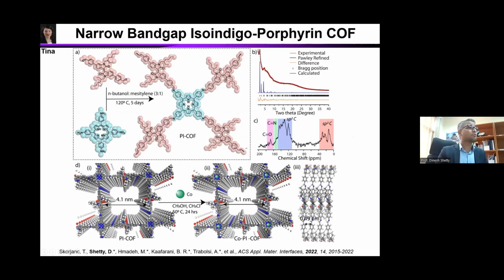Okay, so we use iso-indigo. It's a well-known acceptor. People used it in solar cell applications. But we wanted to use this iso-indigo acceptor with the porphyrin as a donor to make a donor-acceptor system. We ended up getting this COF. It took some time because of this flexible chain. Getting the framework structure was really a nightmare. But we ended up getting this, okay, with multiple conditions.